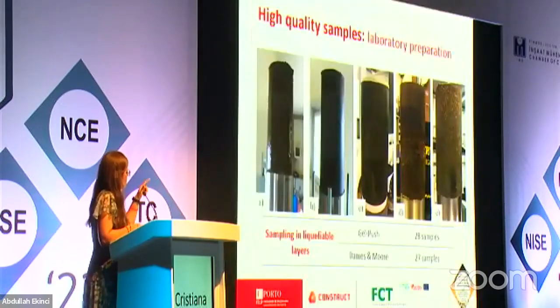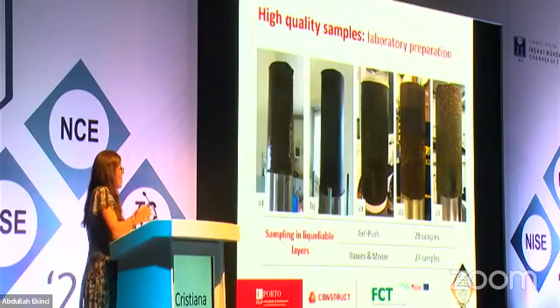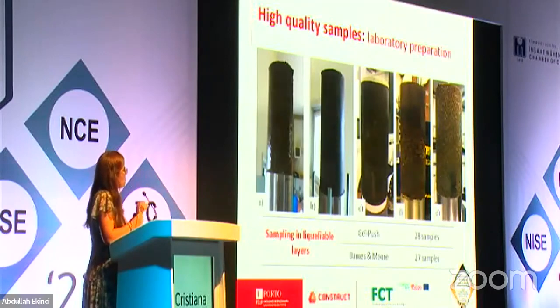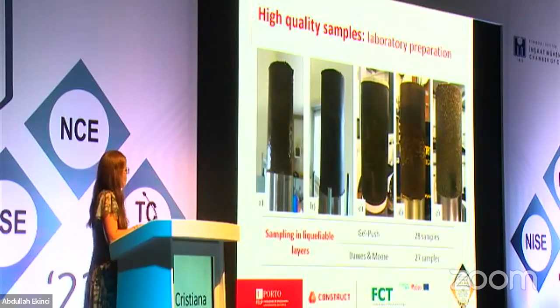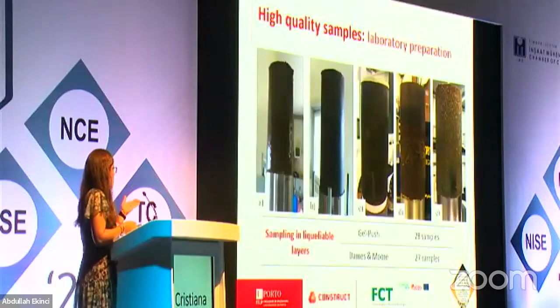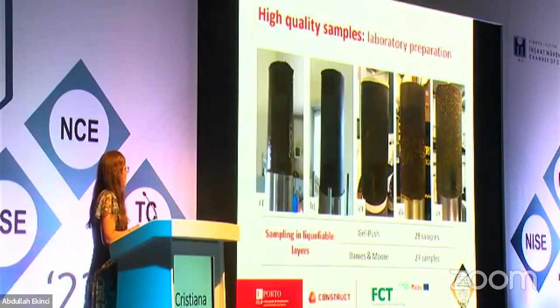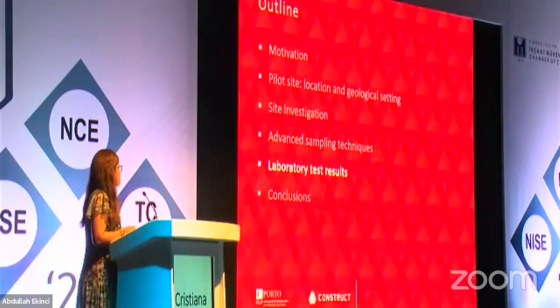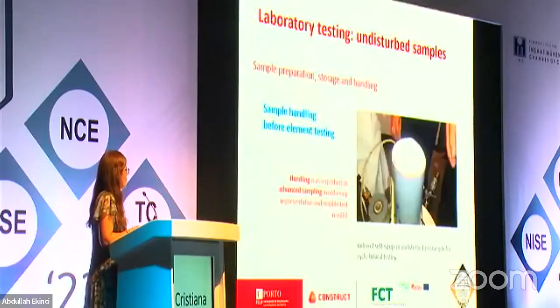And then in some cases you can see that even in this small size sample, this 140 millimeters height, there are some clay layers, with a very smooth surface which indicates the presence of clay, and then other areas which are rougher, like here, where it's definitely sandy. So in the end, we collected a considerable number of samples to study. And then I move to the laboratory test results.